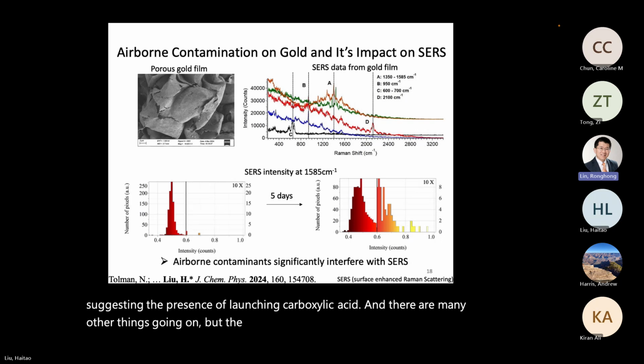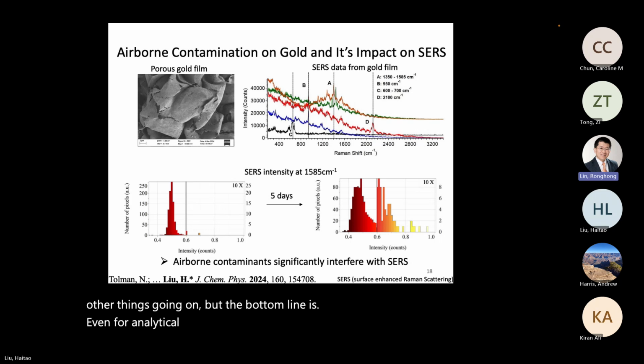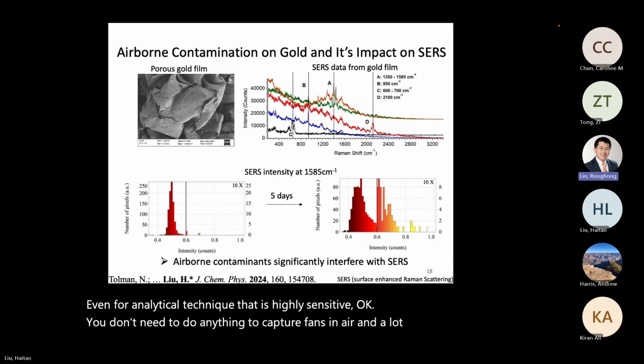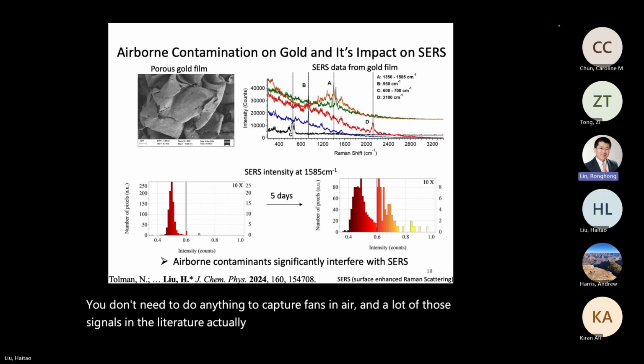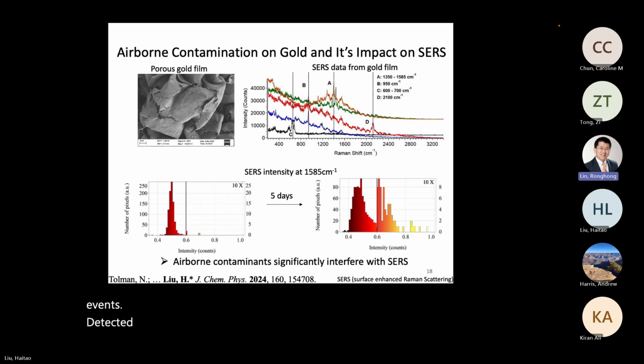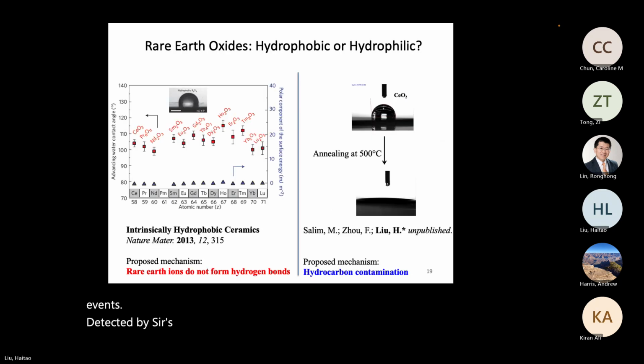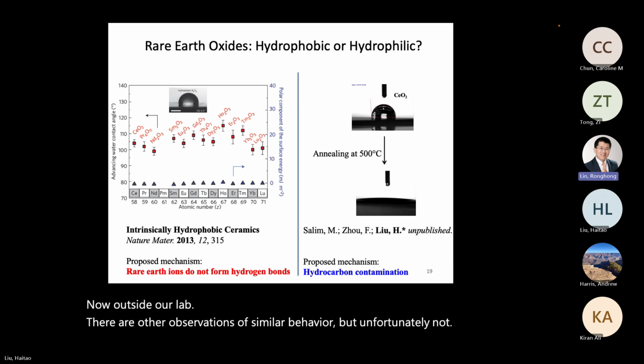But the bottom line is, even for an analytical technique that is highly sensitive, you don't need to do anything to capture things in air. And a lot of those signals in the literature actually were thought to be single molecular events detected by SERS mechanism. Now, outside our lab, there are other observations of similar behavior, but unfortunately not assigned to the correct mechanism.